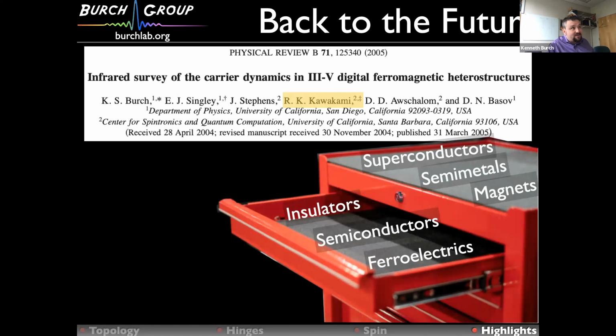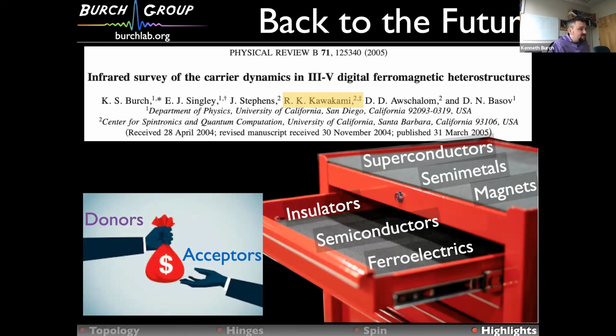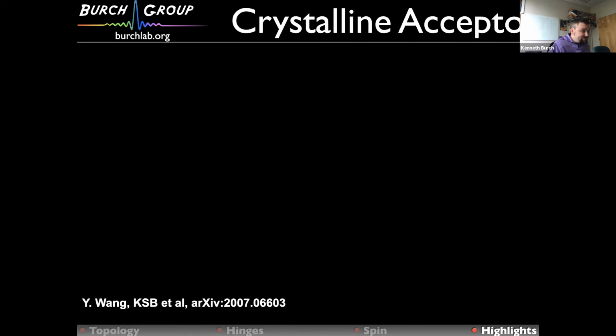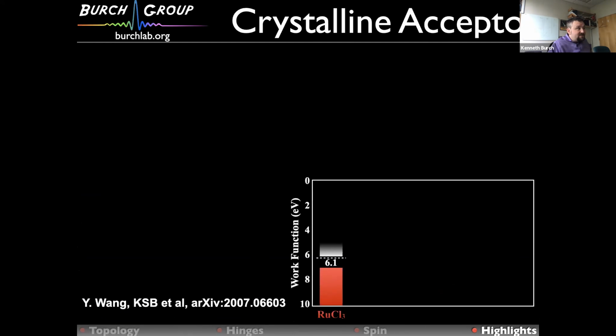You know, 2D materials are a kind of remarkable set of capabilities. We have a huge toolbox of things we can do, but you know, we are all in academia, and we know the importance of also having donors and acceptors, which is the one thing we don't have in this field. And I want to argue to you that actually ruthenium chloride is such a material. It turns out that it has this very narrow conduction band with a small gap coming from the fact that it's a relativistic Mott insulator, but the ruthenium and the chlorine are also very electronegative. And so the work function is roughly 6.1 eV. If I compare that with graphene, it's at 4.6 eV.